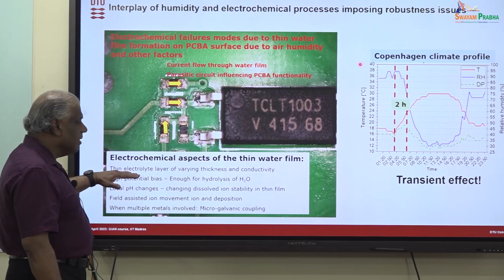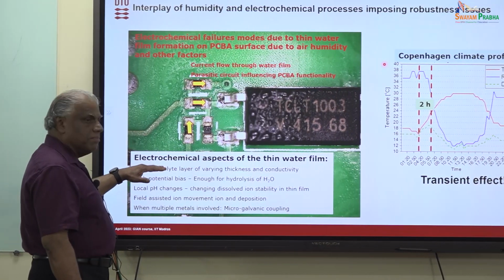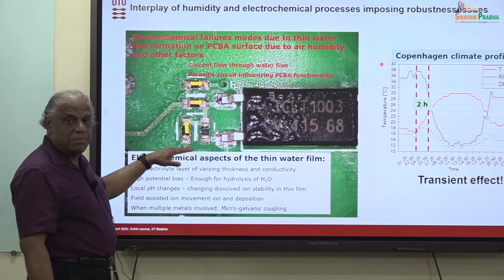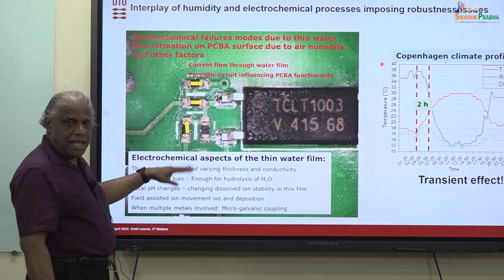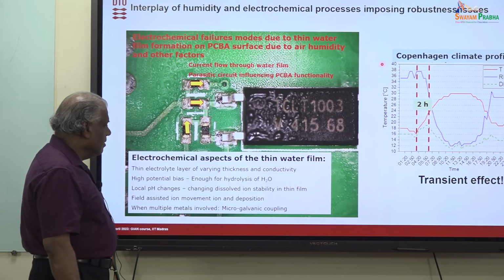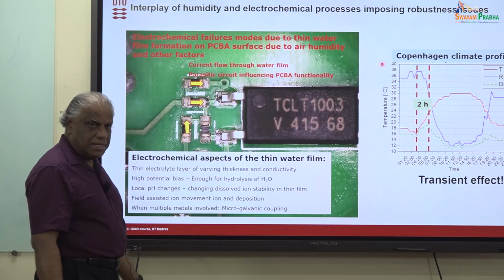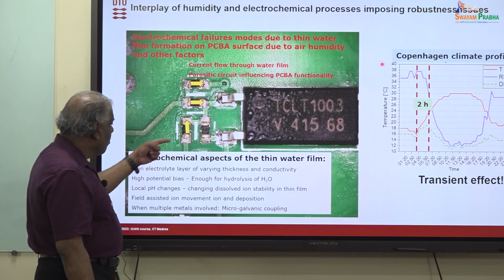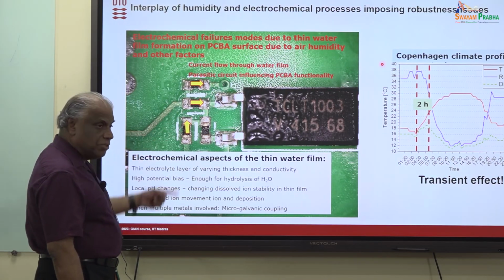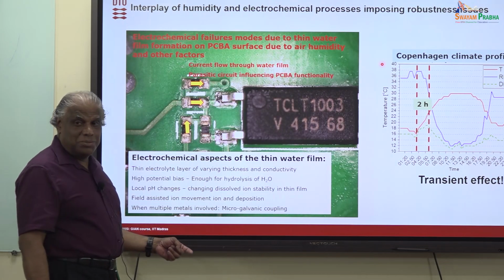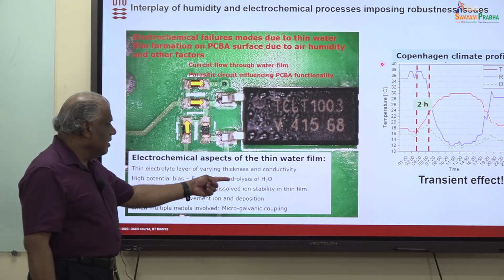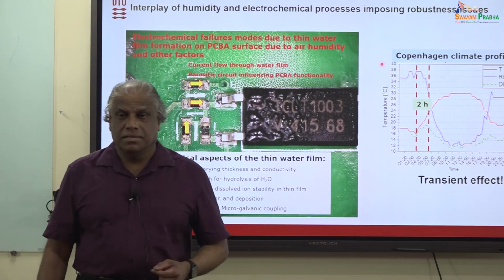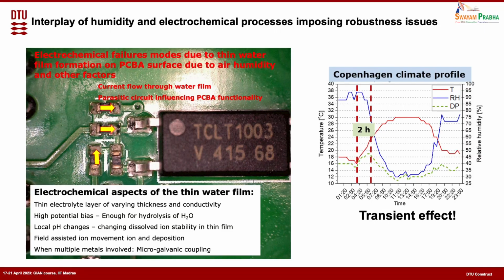It's a very thin layer of water film, probably maximum a few micrometers, but it can also be nanometer scale, this water film thickness, and that means that its conductivity is also limited. That is one thing. Second thing is, always you have a high potential difference between these two. Minimum 2 volts we can take, and that means that is enough for the hydrolysis of water. So hydrolysis of water is a side reaction always when this is happening, at both the anode and cathode, and that has repercussions.